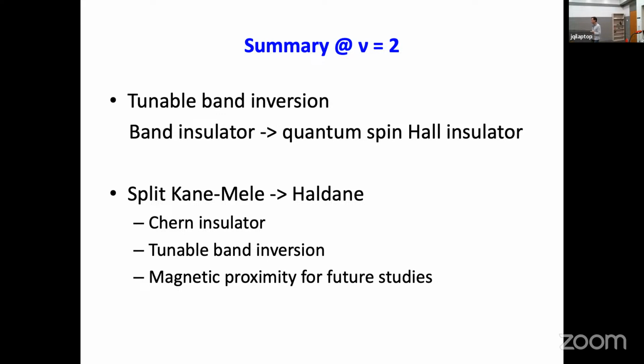So the in-plane work, because I know in many materials this has been previously, like mercury telluride or something, it has been difficult to kill, or I think the way we do is experiments on indium arsenide, I don't remember the semiconductor. It was difficult to see the insulating phase. I think the claim is, if I understand correctly, the previous materials may not be quantum spin Hall, they may just be 2D topological insulators. Exactly. It's protected by time reversal. Yeah. But here it's quite likely it's a quantum spin Hall. Right. That's why there's a very large difference comparing in-plane magnetic field and the out-of-plane magnetic field.